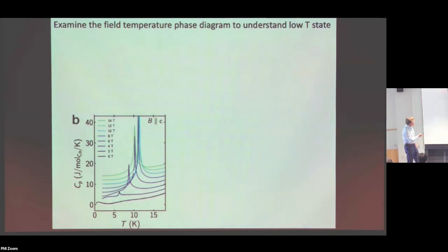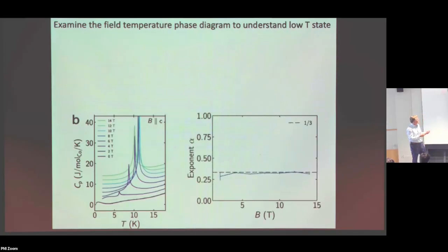But then as we come up to higher fields, now there really is a sharp peak. And what's happened is that there we have a full permutation symmetry breaking, because the sublattices become majority and minority sublattices, and that indicates an Ising-like symmetry breaking. And so then I have a real peak in my specific heat, and actually that's a 3-state Potts model once I have the field on, and that has a known critical exponent of 1/3, and this is our extracted critical exponent from these data, which is actually consistent with that. So we really understand structurally as well as thermodynamically what this phase transition is. It's a 3-state Potts model.